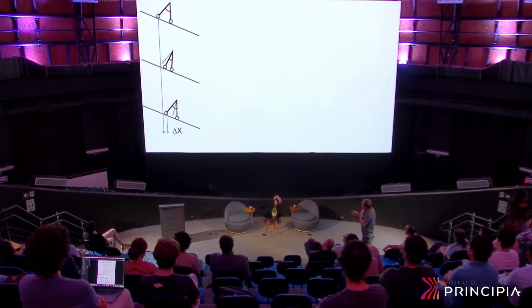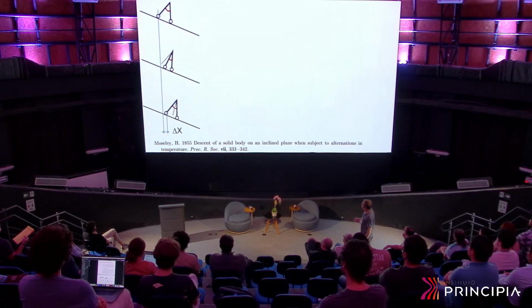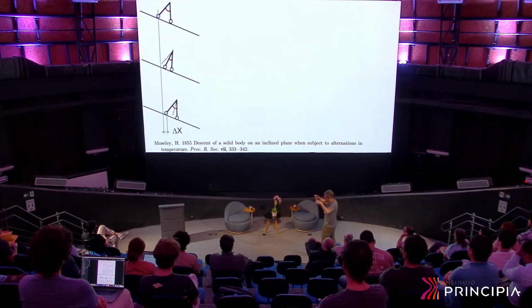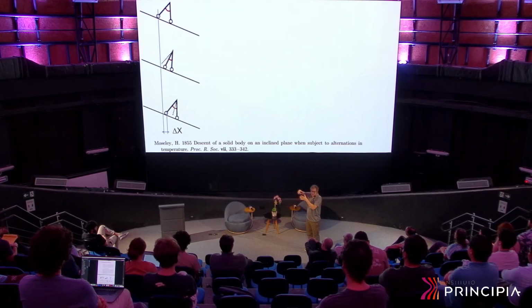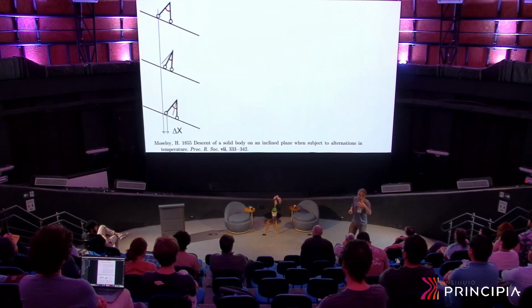Actually, there are a number of toys that make this mechanism function in some way. And when looking to the literature, we found that the first reference to this kind of mechanism, the problem of down movement of objects on inclined planes, is this very old paper by Moseley in 1855, where he describes the movement of plates of lead, I think it was, on top of roofs in some places, that after years he saw that they moved down, and he correlated it with the heating and cooling of this material along a very large period of time.